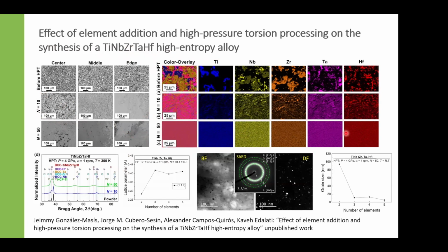and also we have very small grains. So here you can see in the TEM, the grains actually are very, very small. The sample is truly nanocrystalline. There is some degree of amorphization after 50 turns, but you can see here in the diffraction pattern that we have a truly nanocrystalline material. This is the bright field image. This is the dark field image.